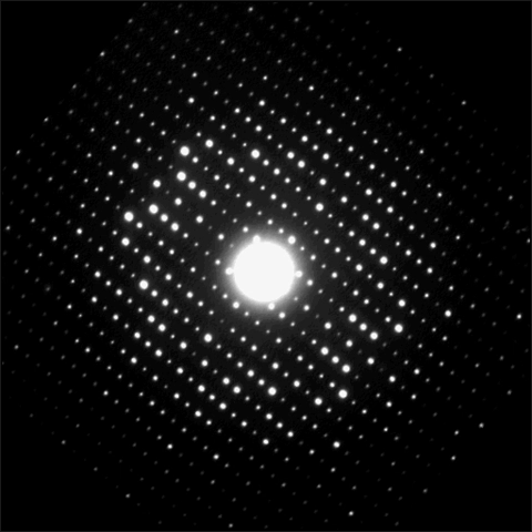In addition to electron microscopy images, it is also possible to use electron diffraction (ED) patterns for crystal structure determination. The utmost care must be taken to record such ED patterns from the thinnest areas in order to keep most of the structure-related intensity differences between the reflections, quasi-kinematical diffraction conditions. Just as with X-ray diffraction patterns, the important crystallographic structure factor phases are lost in electron diffraction patterns and must be uncovered by special crystallographic methods such as direct methods, maximum likelihood or, more recently, by the charge-flipping method.